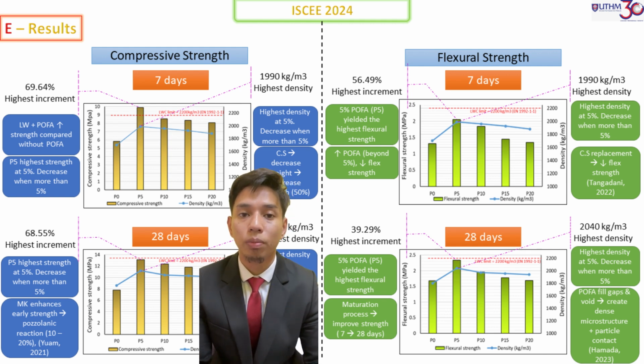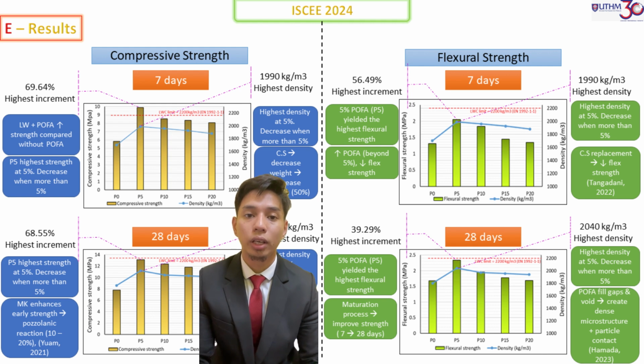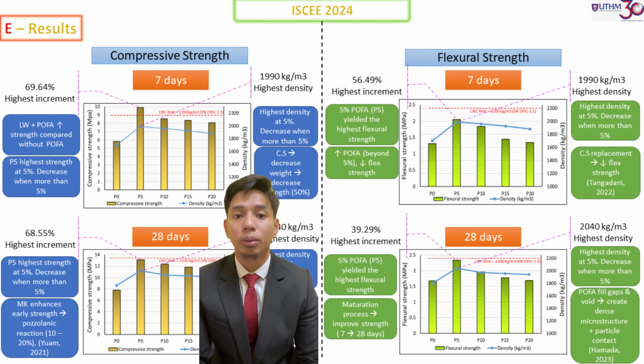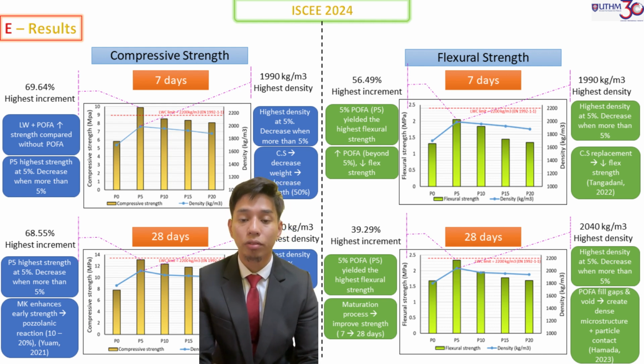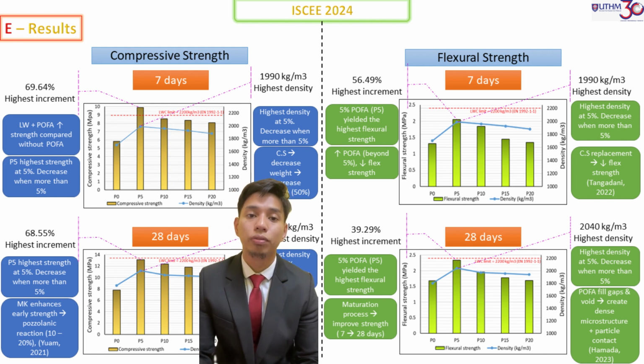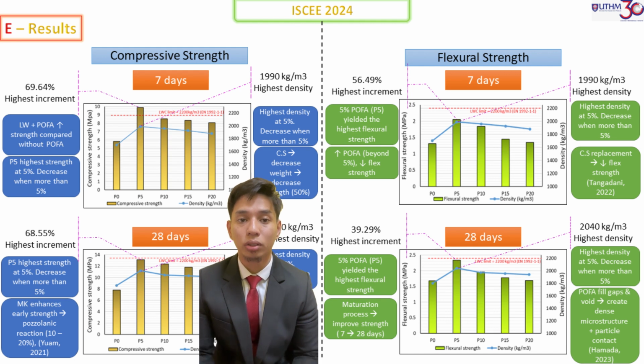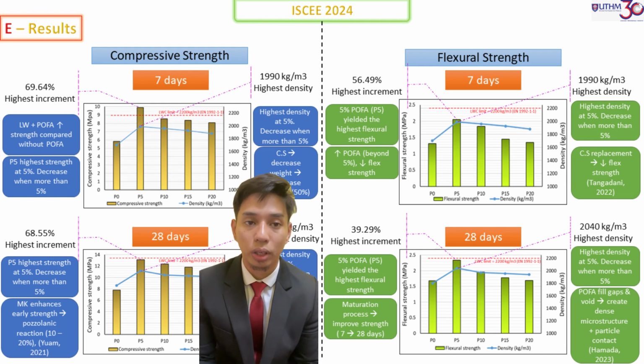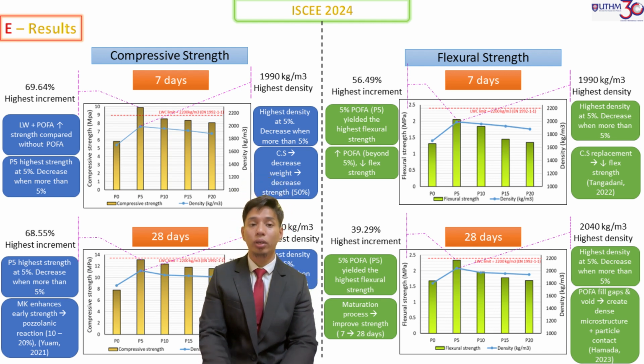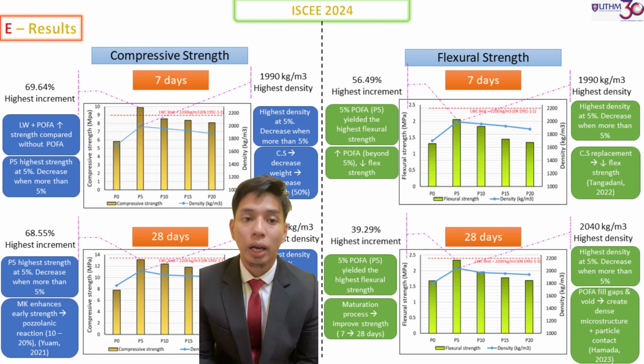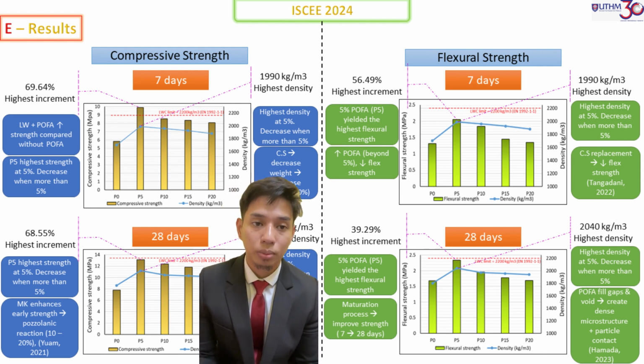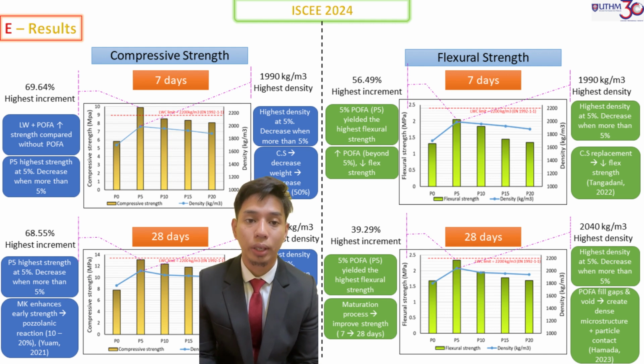So the 5% of POFA yields the highest flexural strength, but when the POFA content is increased beyond 5%, the flexural strength will also decrease. This pattern is shown in the graph. And for the density at 7 days, it belongs to the P5 also, with 1,990 kg per meter cube. And again, the coconut shell replacement will decrease the flexural strength.